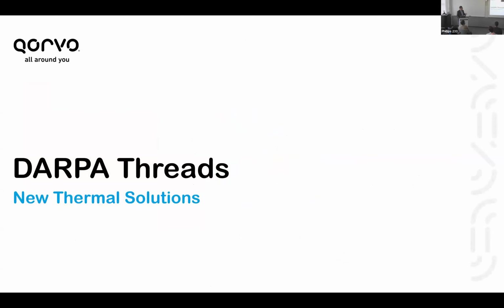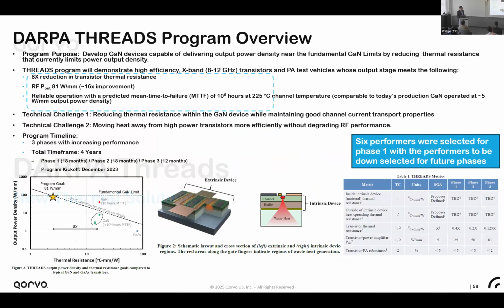And as I mentioned, as you go to higher frequency, you have more and more heat generated. This is another program, the DARPA THREADS program. We are looking at using diamond to help with the heat dissipation by placing diamond on both the top side as well as the bottom side, in order to get the GaN HEMT power to meet the goal, like 81 watts per millimeter. This is a very high power, about 16 times compared to what we can get nowadays. So the thermal issue is, I would say, the final issue once we go to a higher frequency regime, because of low efficiency.